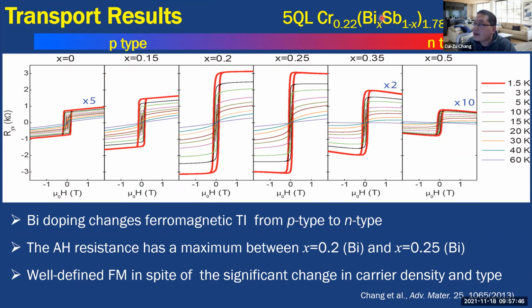So here is 5 quintuple layer chromium-doped bismuth antimony telluride, and we systematically change the x, the bismuth doping level. This is pure chromium-doped antimony telluride, and 15%, 20% up to half of the bismuth doping in the sample. From this data, we can see that when you change the bismuth doping level, the ferromagnetic material can change from p-doped to n-doped. So from p-doped to n-doped, there is definitely some point where we could realize the insulating ferromagnetic topological insulator.